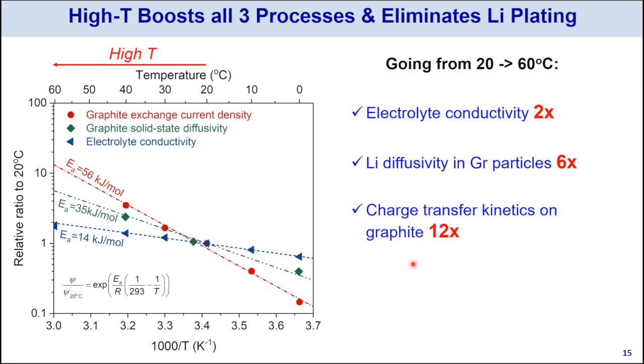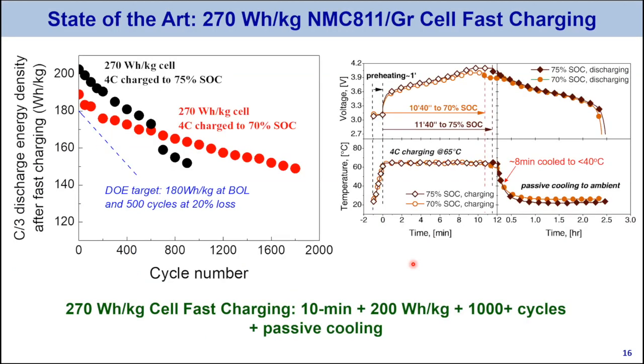Okay, so with all these powerful principles and mechanisms, we can carry out fast charging in numerous systems involving many different materials. Here I give you one example, which involves a 270 watt hour per kg NMC 811 graphite cell, and we can put it at a 4C fast charging to 75% SOC, and the acquired energy at the beginning of life is a little over 200 watt hour per kg. And you can see that we can easily cycle 900 times, right?